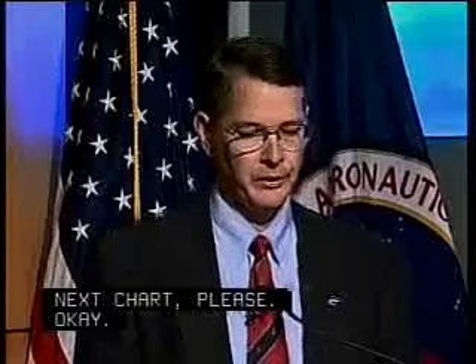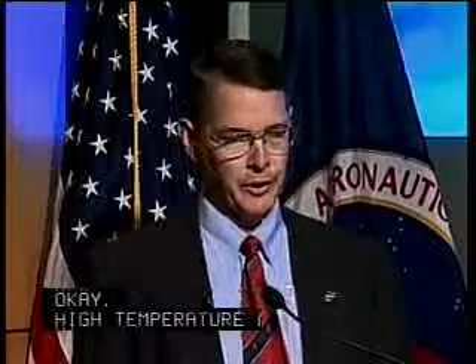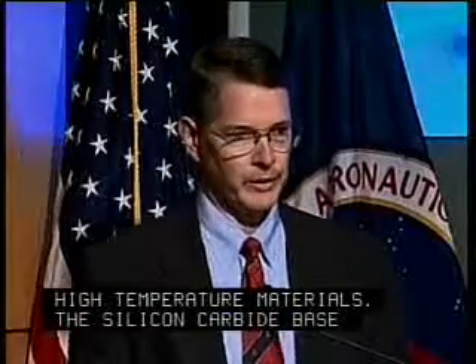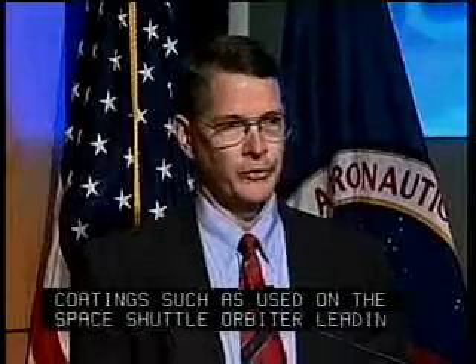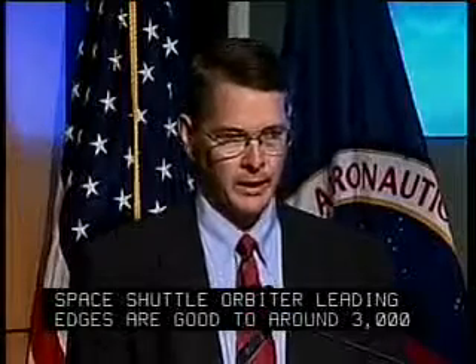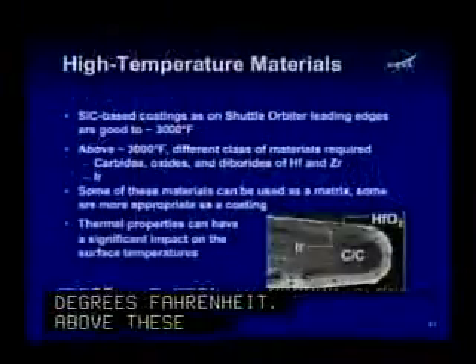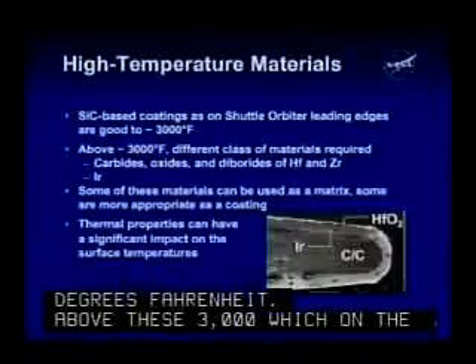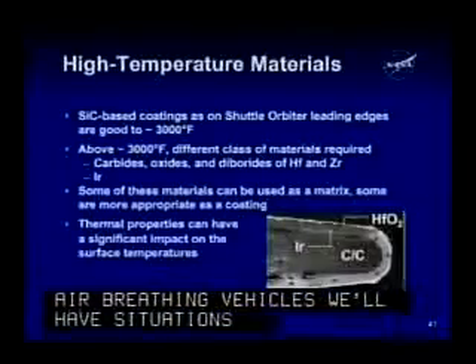Okay, high temperature materials. The silicon carbide based coatings, such as what's used on the Space Shuttle Orbiter leading edges, are good to around 3,000 degrees Fahrenheit. Above 3,000 F, which on these air-breathing vehicles, we're going to have situations where we're above 3,000 F.